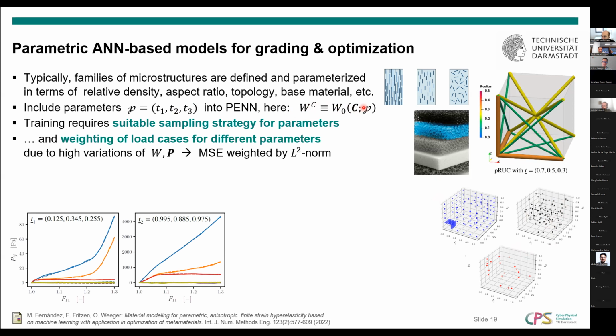Now, when we look at the mechanical behavior of these microstructures with the different parameters, we see that their mechanical behavior can be very different. So basically here I have a microstructure where the parameters are close to 1, which means that all the struts are very thick. So I have a stiff response. I get very high stress values here going up to 4,000. Whereas of course, when I make the struts thinner, I get a softer behavior. So here I have stress values up to 80. So we have like 2 orders of magnitude difference in the values that we're trying to fit with our neural network.